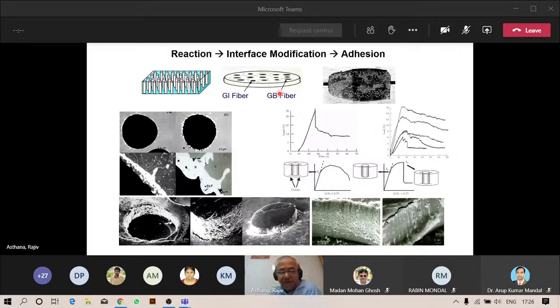Our idea was to eventually grow a single crystal NiAl matrix with sapphire fibers embedded in it. We also modified the interface in the system using different alloying elements. So I'm showing you the example of how ytterbium, a highly reactive rare earth element, modified the interface between the sapphire and the NiAl matrix around it. And when you do the fiber push out to find the bond strength, you see high bond strength.